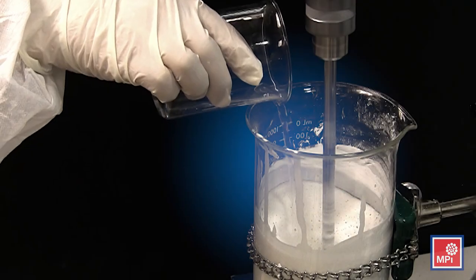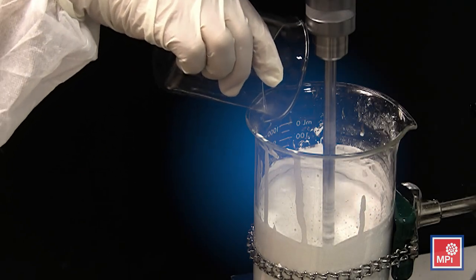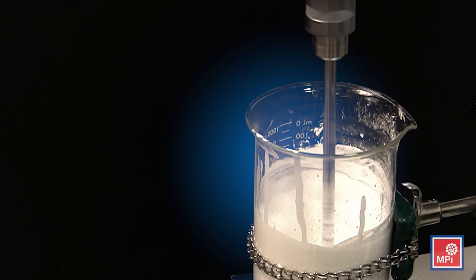The retained water can now be added and the mixing speed reduced to 800 revolutions per minute. We recommend mixing this final wax dispersion for about three minutes.